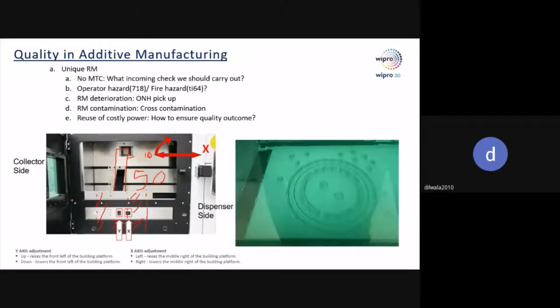This is already exposed powder, right? So we need to do the filtration so that we remove all the particulates from them. So out of 30 kgs, after doing IPCM, we basically recover like 28 kgs of powder. Now this powder is recovered and it can be reused.